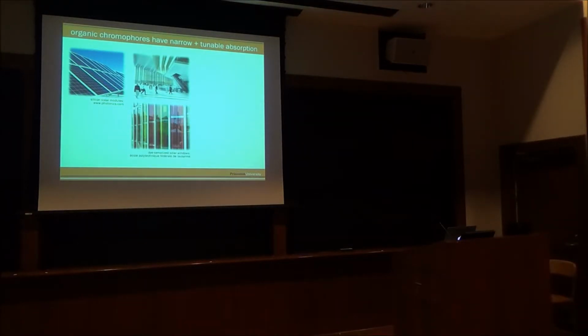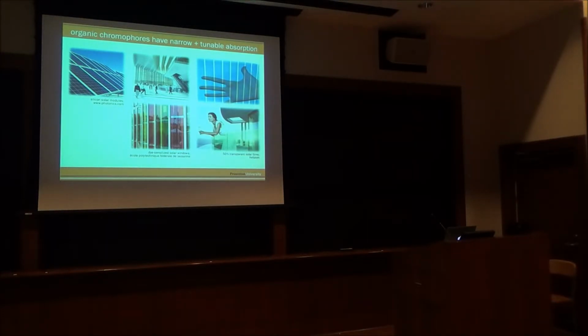So I think organics are appropriate for this kind of application because organics have very narrow and tunable absorption. You can tune it by playing with the chemistry. So this is, again, silicon, just for contrast. These are dye-sensitized solar cells, so a slightly different technology, nonetheless requiring organic semiconductors. And look, depending on what dye you use, you can access different colors. Heliatek has made these transparent or semi-transparent solar films. And again, it's by tuning the optoelectronic properties of these organic semiconductors.